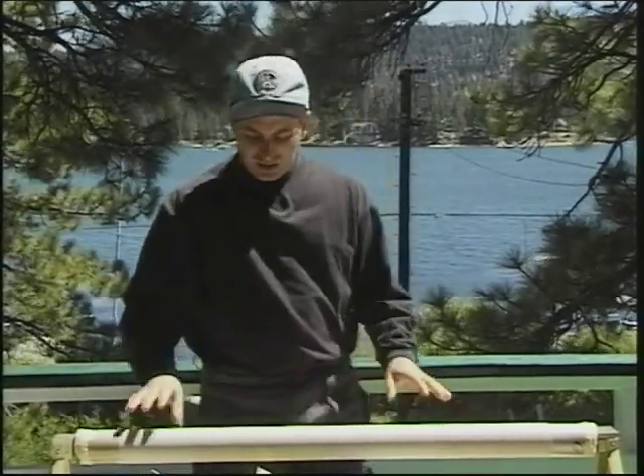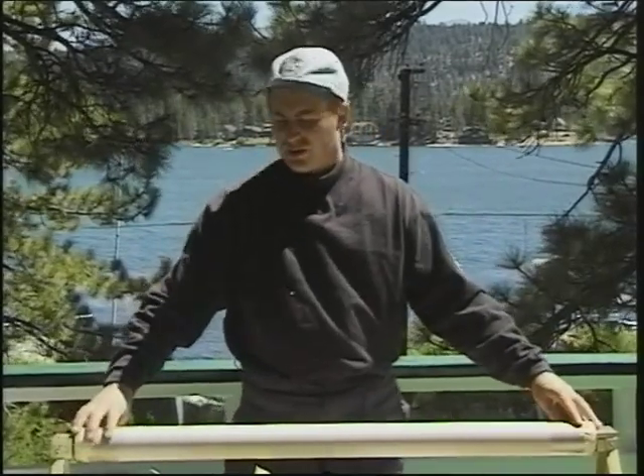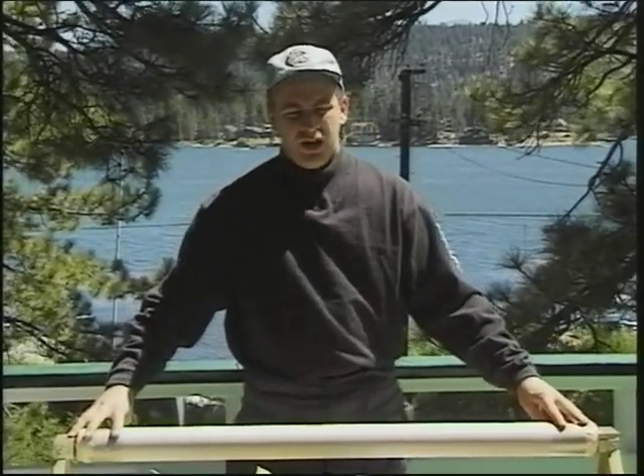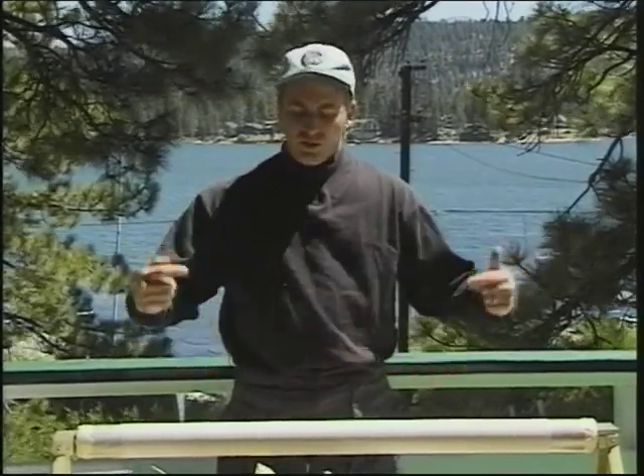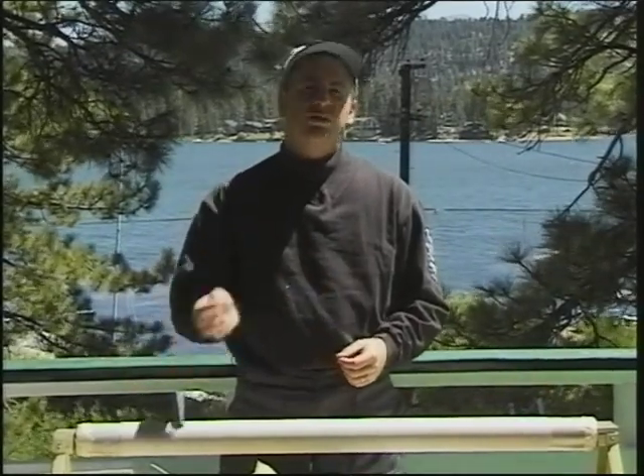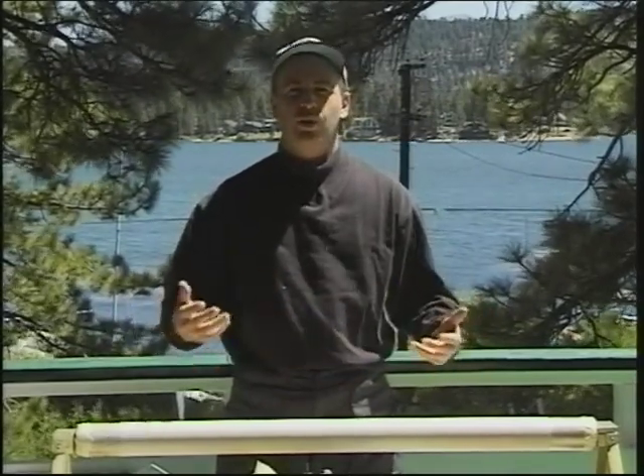When you're talking about creating a composite structure with a tube, it really is that. Creating a composite structure is much more than just slopping on a bunch of epoxy over glass cloth until it becomes clear, and then you're left with a very heavy mess on your hands. The aim of creating a composite structure is to wrap the tube with a ratio of cloth to resin of roughly 50-50. That means most of the people out there are using way too much resin in their layups.